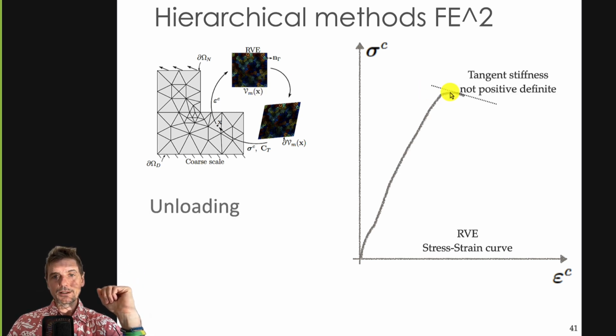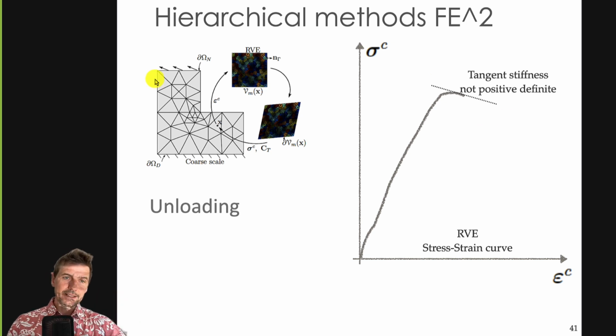And this is where the problems take place, because you now have a material stiffness tangent, meaning d sigma c, d epsilon c, so partial sigma, partial epsilon, which is now negative. And why is that a problem? Well, because you are solving a partial differential equation here, which is an elliptic equation, which means that certain coefficients need to be positive for that equation to be elliptic. And now that particular coefficient, which is the stiffness, is no longer positive, it's negative.